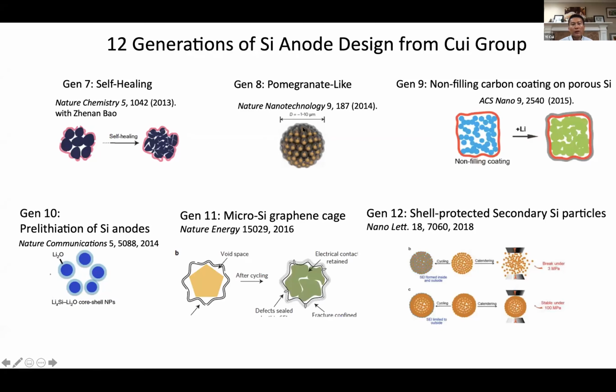This generation 8 design of packing the silicon particles together into a secondary particle is actually a very powerful concept. You coat the outside of the secondary particle with a coating to prevent electrolyte from coming in. Nanostructures are also oftentimes very hard to pack nicely to have high volumetric capacity or high volumetric density. But if you pre-pack them together, it is possible to realize the potential of silicon while still having high volumetric capacity. We show that's possible.